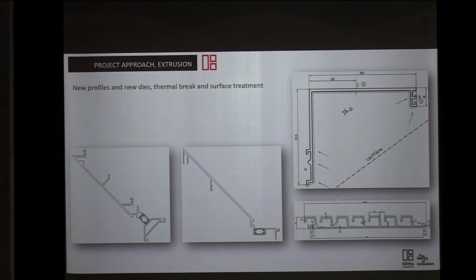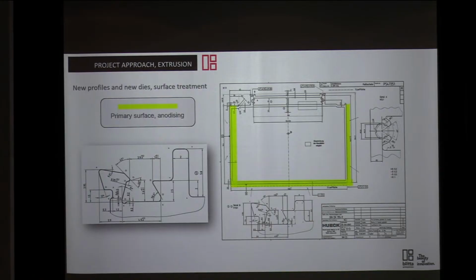This one is a profile from a TBS clinic in Almere. Very difficult to get the powder coating everywhere we want it. So those are also practical solutions, examples of what you come upon. Here again is that other profile. The yellow line is the outside, so it's visible, but it runs out on the bottom part of the yellow line, and as I said, you have an aluminium silicium alloy, so there can also be some visible marks on the profile. So that has to be settled.